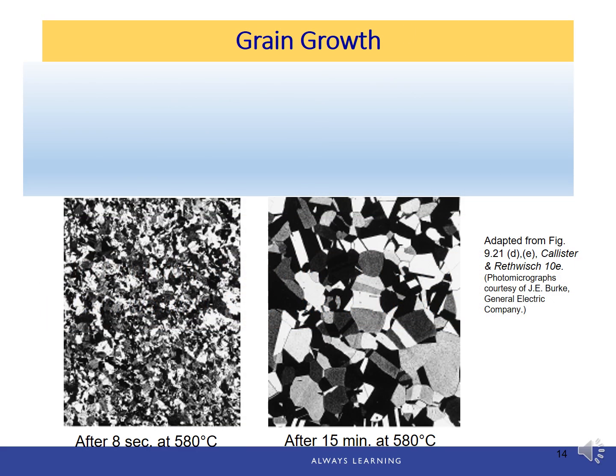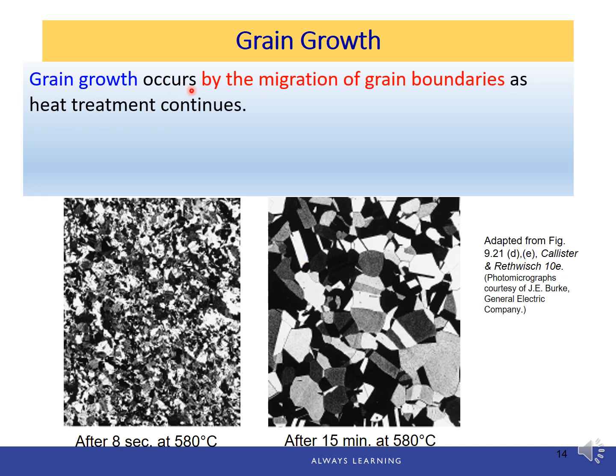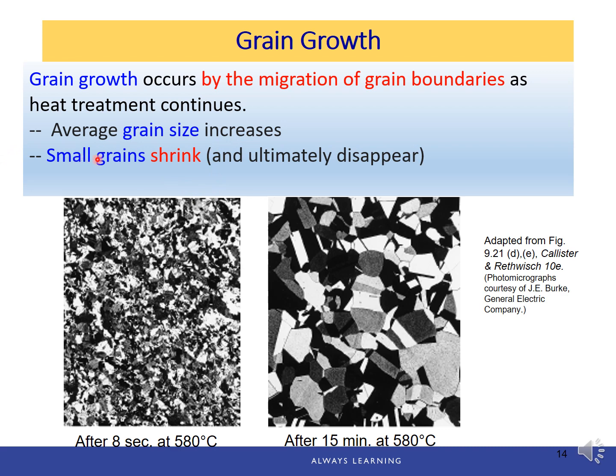And after recrystallization, if the heat treatment continues, the next stage is grain growth. It doesn't have to happen if you don't hold the specimen at the elevated temperature. But if we do, as it continues, the grains start to grow and become bigger. It occurs by the migration of grain boundaries as heat treatment continues. And the average grain size increases during grain growth. Small grains will shrink and ultimately disappear, and large grains continue to grow. They will consume the smaller grains.